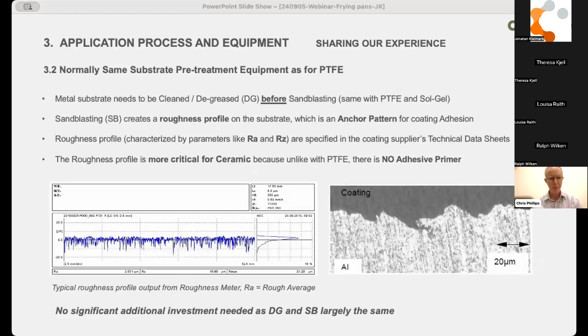With both technologies, the substrate needs to be pre-treated, which means degreasing before sandblasting. The roughening part is slightly more critical for ceramic non-stick because unlike PTFE, there's no adhesive primer. With PTFE, that primer acts like glue onto the metal substrate, whereas ceramic relies purely on the roughness profile to form an anchor pattern, and then it's a lock and key mechanism of adhesion. So you just have to observe those parameters slightly more carefully, but all factories have a roughness meter and are capable to do this. Next slide.